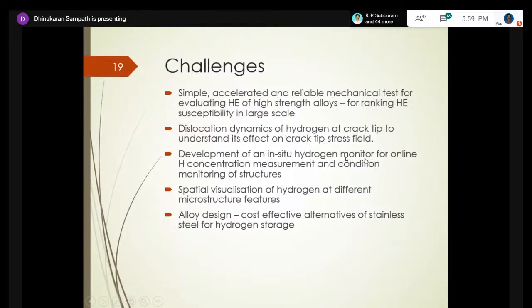Development of an in-situ hydrogen monitor. This is one key instrument which we can use to measure the hydrogen in the material or the surface, whether it is below the critical level, so that we can operate it. One can use it for condition monitoring. Once it reaches some critical level, for example in steel, I'm not sure about this, but they just heat the material to a certain temperature like 250 degrees centigrade, the hydrogen is all released, and then the material will behave like a normal material unless there is phase transformation. So that's one area to look at for condition monitoring.